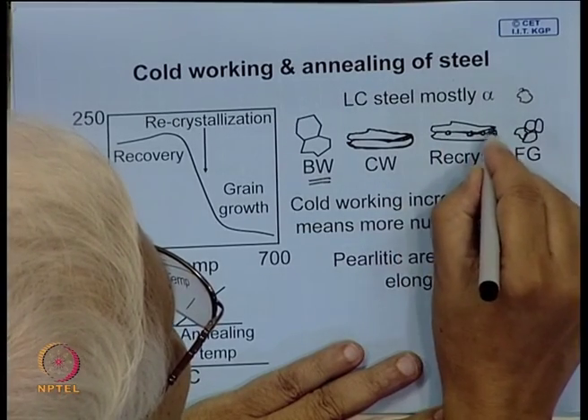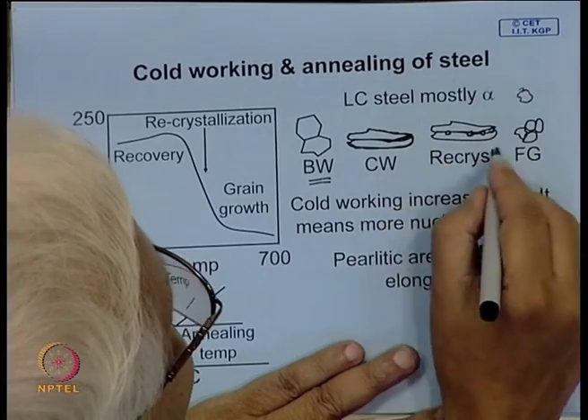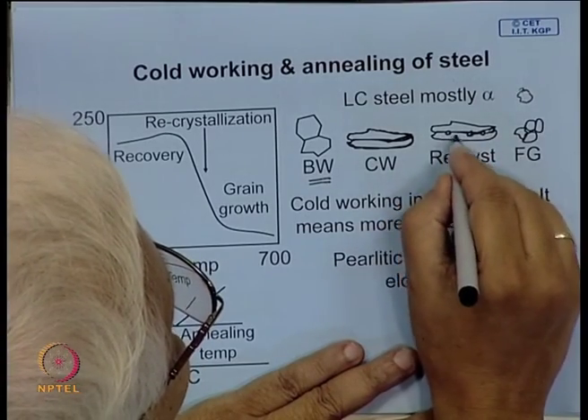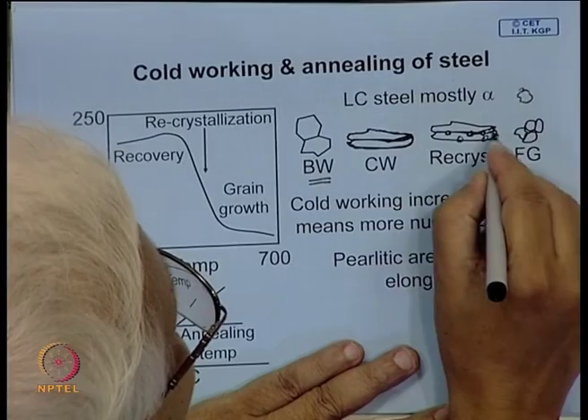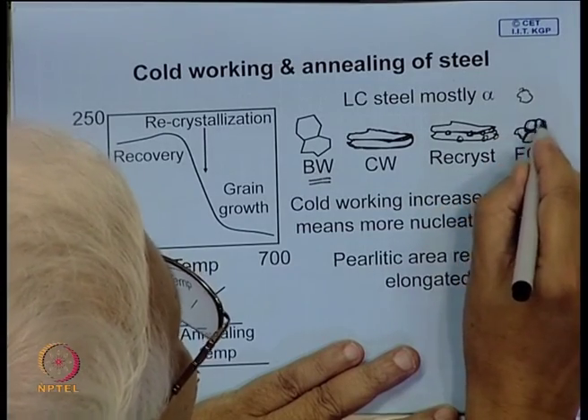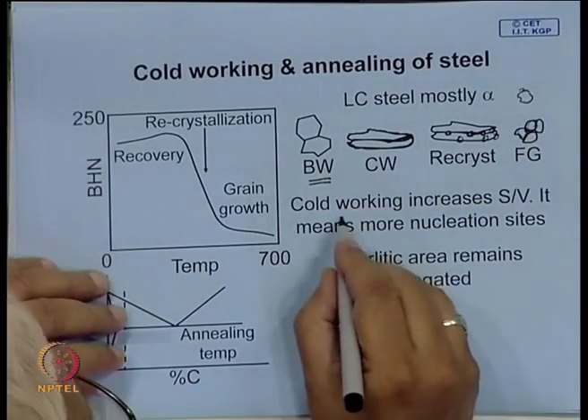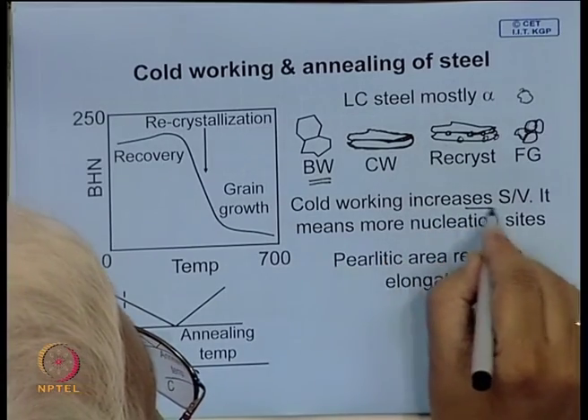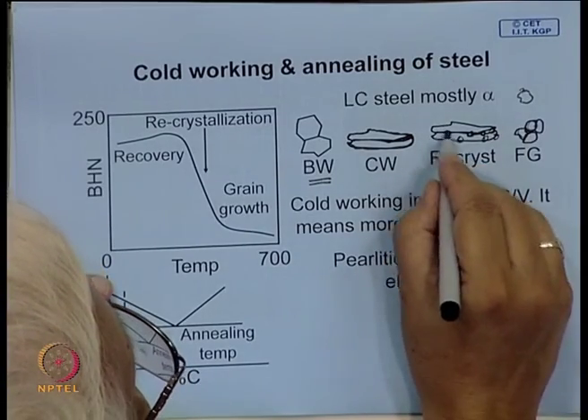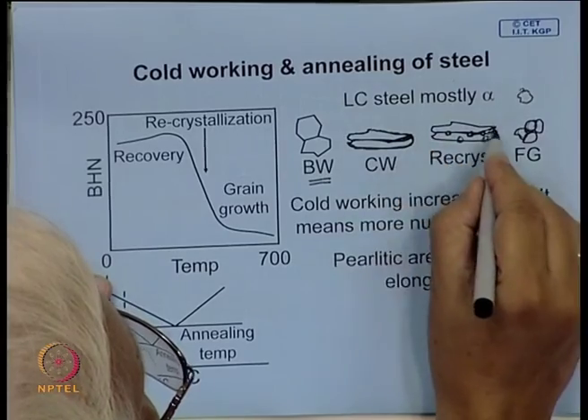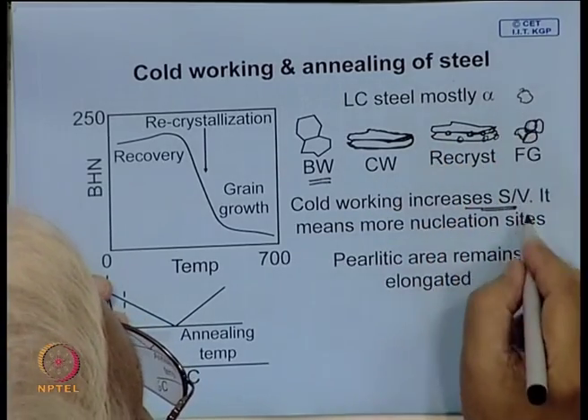So these are the nucleation sites, and when these grains grow, finally all of the deformed grains are replaced by these fine grains. Now, cold working, in fact, increases the surface area to volume ratio, so you provide more sites for nucleation of strain free grains.